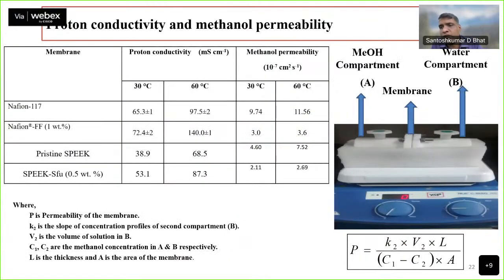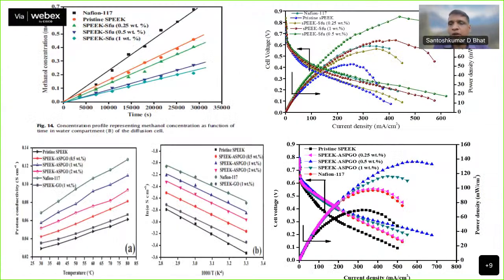Okay, so once we do this, we also do conductivity and methanol permeability to understand the electrochemical selectivity. So in the direct methanol fuel cell, which is very important, once we do this, we get a proper electrochemical selectivity and generate a concentration profile. So once the concentration profile is generated, you can go for the direct methanol fuel cell study, where the similar membrane can be targeted for the direct methanol fuel cell, where we see the performance IV characteristics.